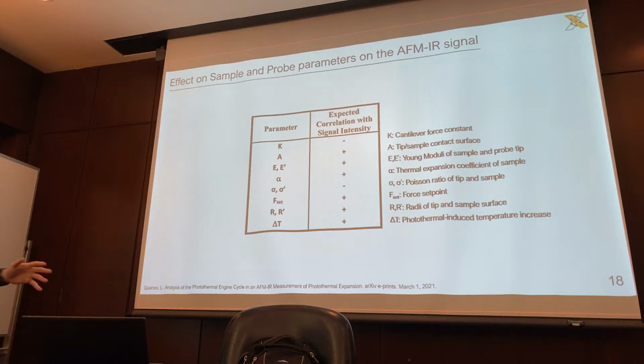So here's the table that I promised you that breaks down everything into a more digestible form. Here are the different parameters and their expected correlation with the AFMIR signal itself. In terms of the cantilever force constant, which I explained a little bit earlier, we're supposed to see a negative effect on the AFMIR signal. In terms of the tip-sample contact surface, we want to maximize that in order to optimize our signal.